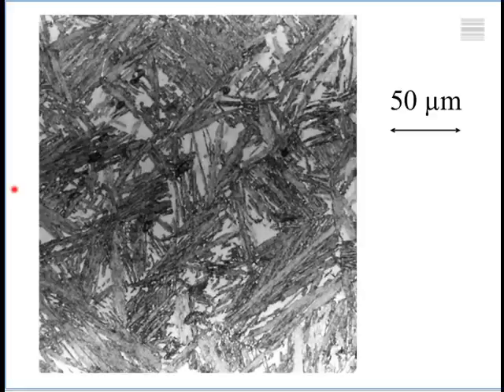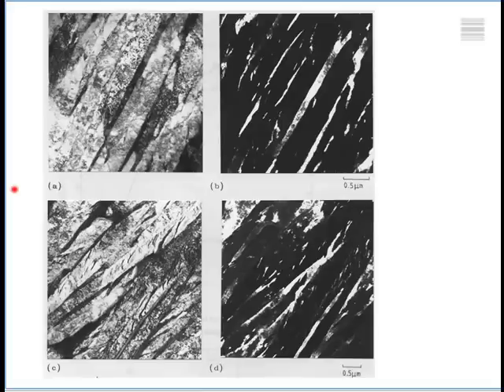If I do that, I get rid of the large islands of austenite. This beautiful microstructure without the large islands. This is the steel where I've reduced the carbon concentration by a factor of 2. These are the austenite films and bainite. There's no coarse regions of austenite.